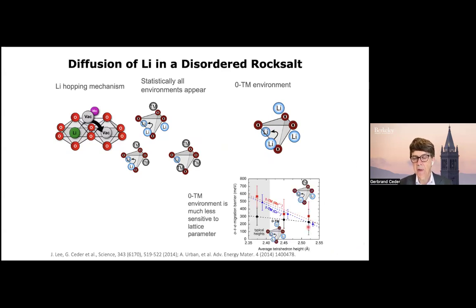If you look at what's called the 1TM channel, which is this one, which is active in layered materials, the activation energy goes up a lot as you contract the tetrahedron. Whereas if you take a 0TM channel with only lithiums around it, you still have fairly low activation energy even when you contract that tetrahedron.